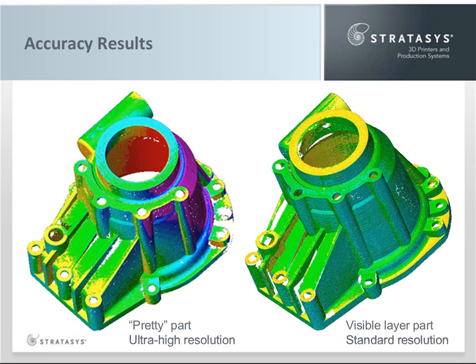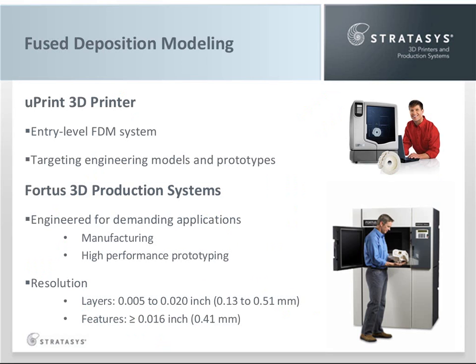As you can guess, the one on the right was printed with fused deposition modeling. But it's from a Stratasys entry-level printer, the U-Print, which is optimized for printing concept models and prototypes. I will show in just a bit the accuracy of the production-oriented Fortus line that is engineered for manufacturing applications. This will be demonstrated by thorough analysis that no others, to my knowledge, have published. While FDM technology may not be ideal for ultra-high resolution parts like jewelry, it is engineered to meet the stringent accuracy demands of functional prototypes, fixtures, and finished goods. The FDM system resolution: layers from 5 thousandths to 20 thousandths of an inch, and extrusions that produce features as small as 16 thousandths of an inch.